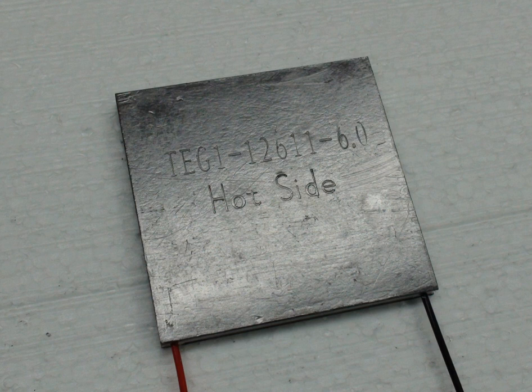The ability to selectively decrease the lattice conductivity results in reported ZT values of 1.86 plus or minus 0.15, which are a significant improvement over current commercial thermoelectric generators, which have typical figures of merit closer to 0.3 to 0.6. These improvements highlight the fact that in addition to development of novel materials for thermoelectric applications, using different processing techniques to design microstructure is a viable and worthwhile effort. In fact, it often makes sense to work to optimize both composition and microstructure.